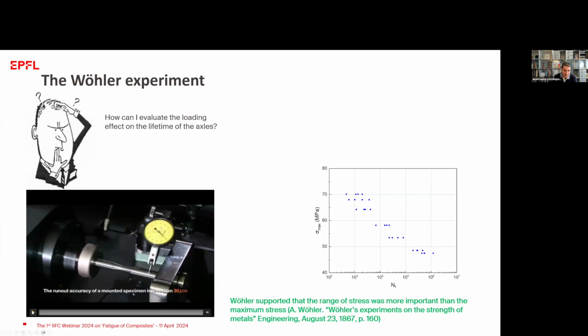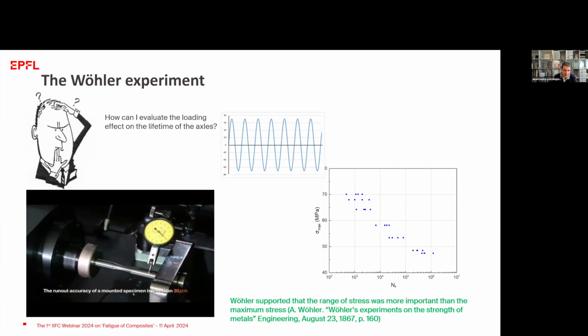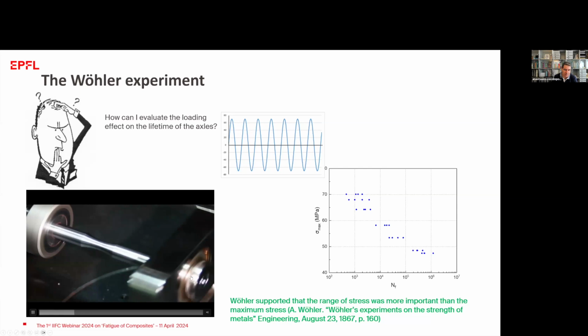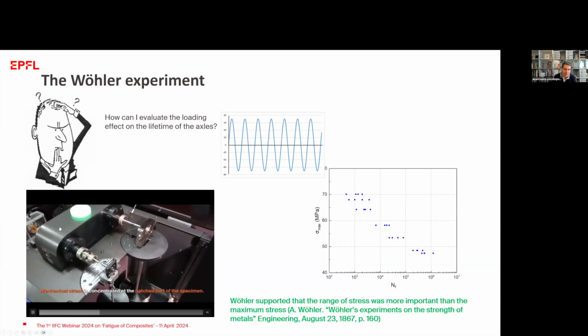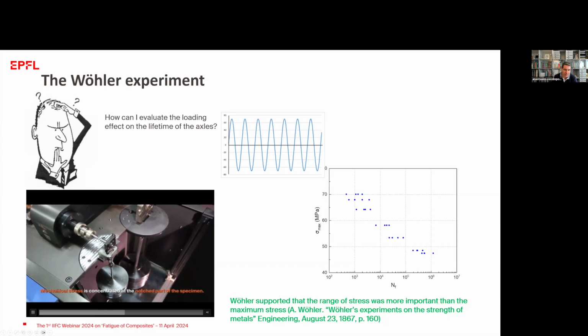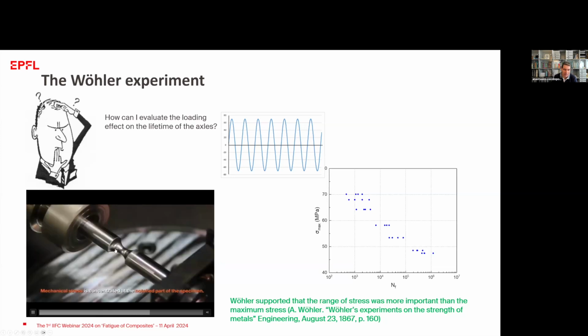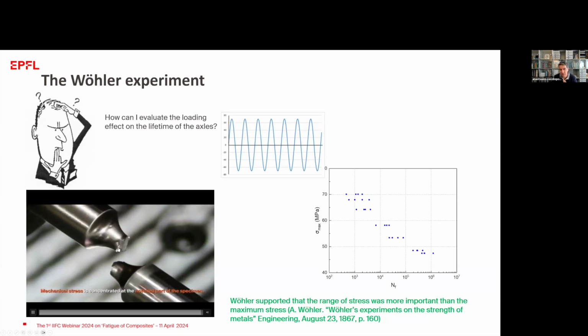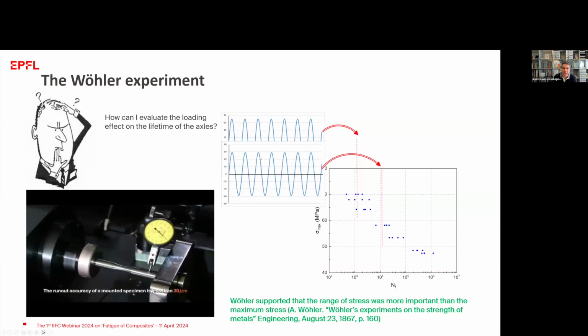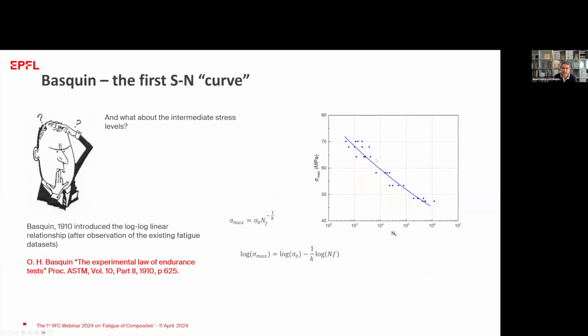So here I collected from the net an experiment. It's a small video showing the experimental procedure, similar to what Wöhler did. We have a rotating specimen here, this small specimen. We have a load here that causes the stress, and then after some rotations, we can see the failure of the specimen in the middle, which is attributed to fatigue. So we described what happens here when we put the specimen in load, we test it and we record the number of cycles to failure. So this is the procedure that I described before, and then we have the question, what happens in between?